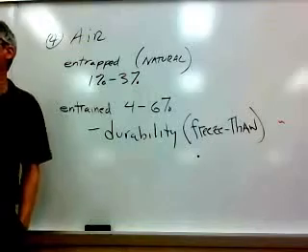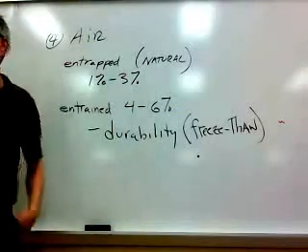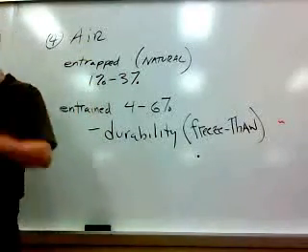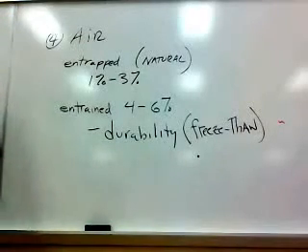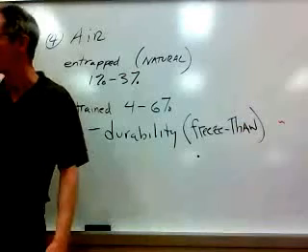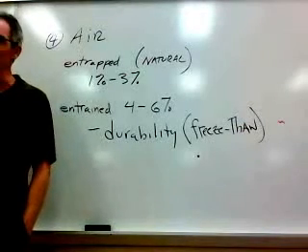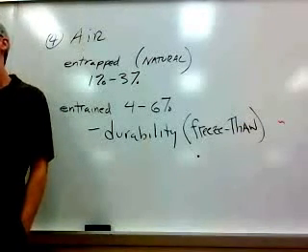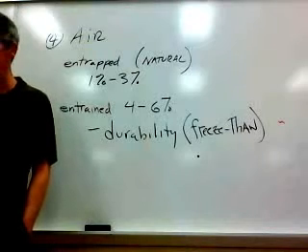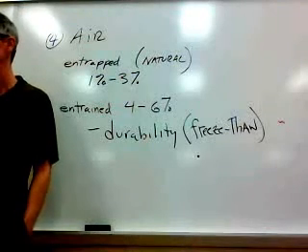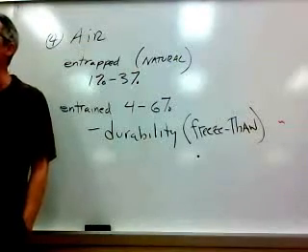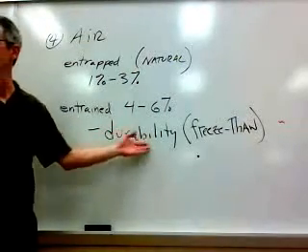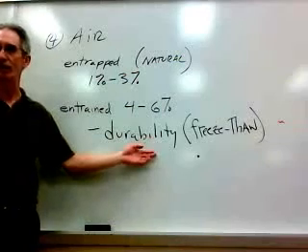It does other stuff. You said, hey, it makes it lighter. Yeah, adding more air, air doesn't weigh a whole lot, so if we have concrete and it has more air in it, I guess it does weigh less. But we don't really do it too much for that. It does actually make the concrete more workable when you do this. It makes it more fluid, but we don't do it for that. If we're going to use air entrainment, we're going to key in on durability.